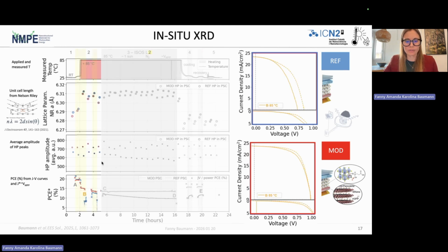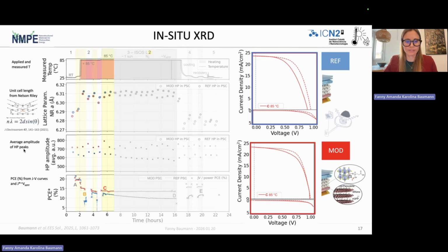And as we go to 85 degrees, we start to see major changes. We have an initial very sharp voltage drop, and that recovers after a while in the reference cell. But in the start, this sharp voltage drop really shows up in the performance here at point B. And we believe that this is because in the MXene, we have an additional MXene layer in the modification that will really be able to compensate for some of the strain as this lattice parameter increase is very sharp.